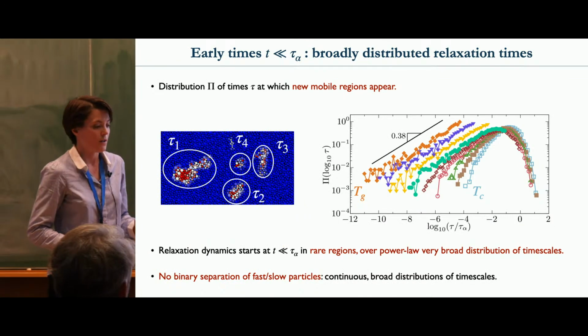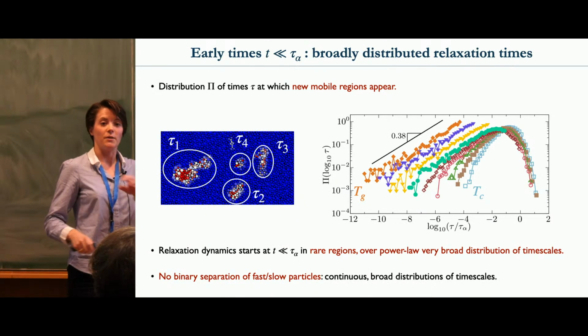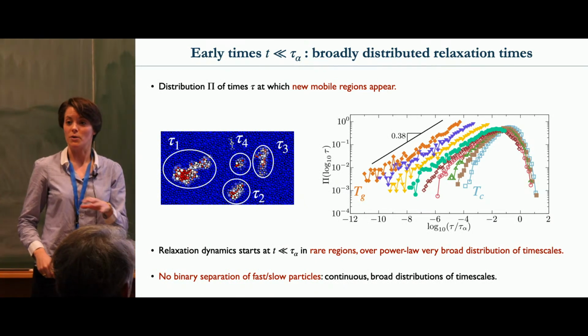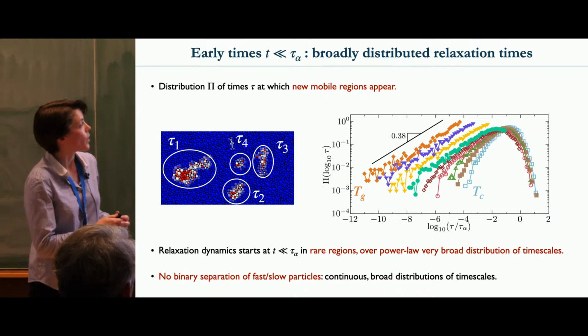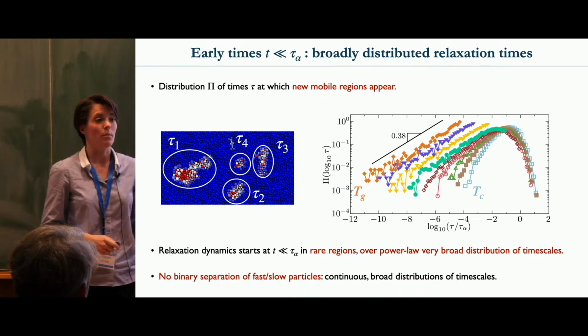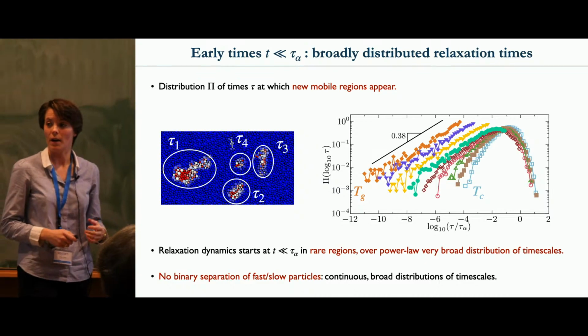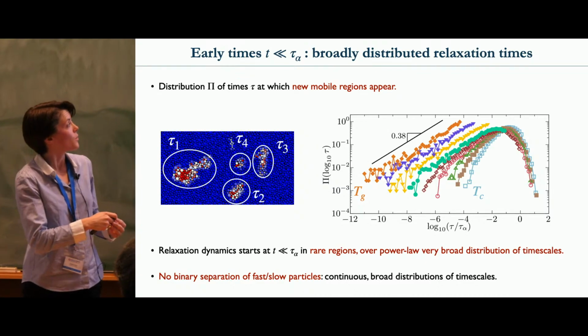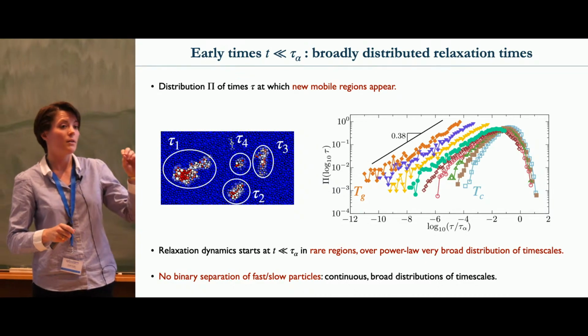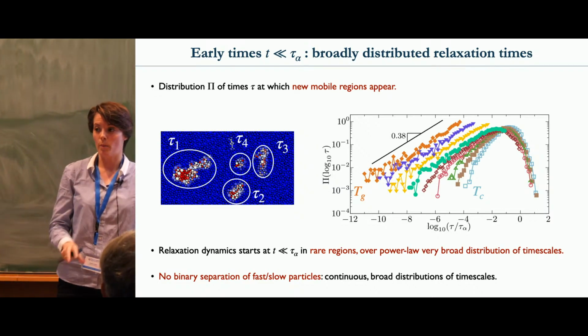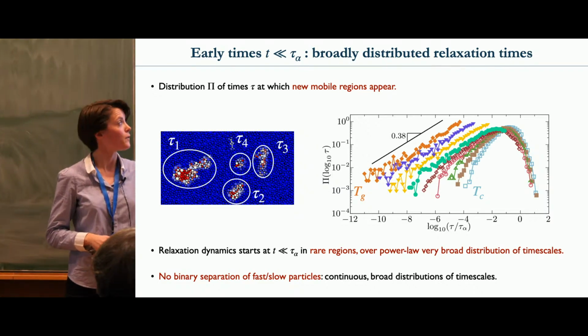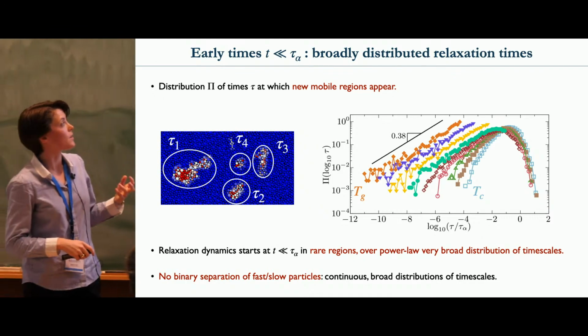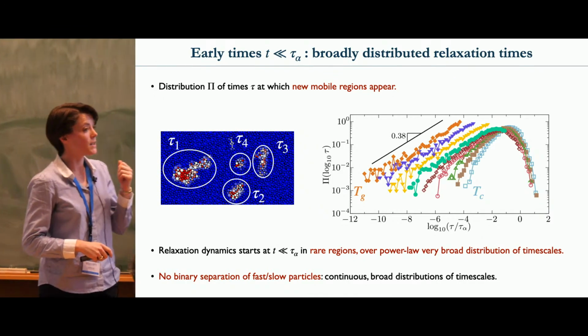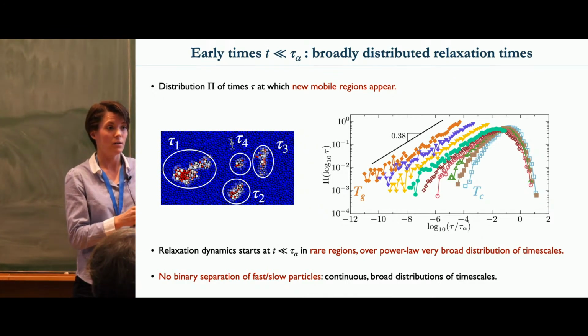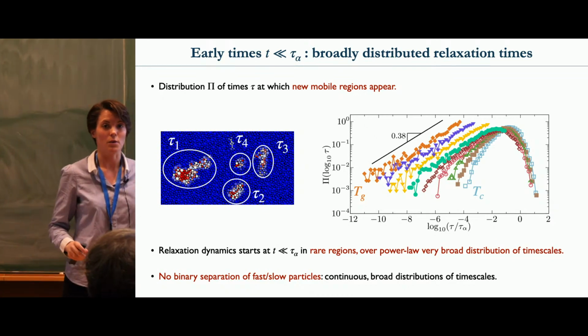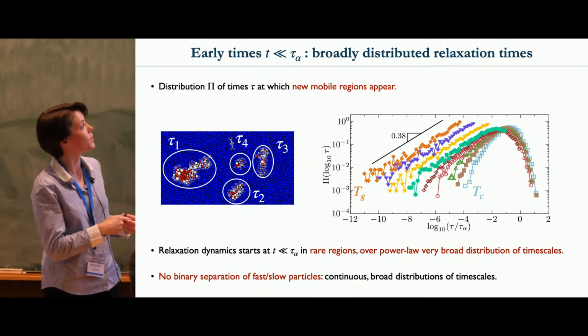So let's concentrate first on the early times, which give rise to this power law in the spectra. I want to explain a bit more what's happening here, and especially quantify what we observe. At short times, regions start to pop up in the configuration where relaxation starts. And we see that this doesn't happen on a fixed time scale. It's a continuous process, and we want to quantify it a bit more.